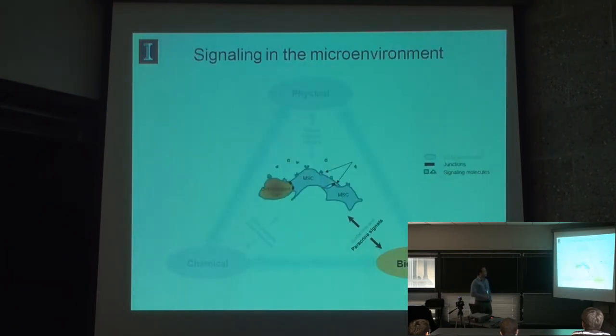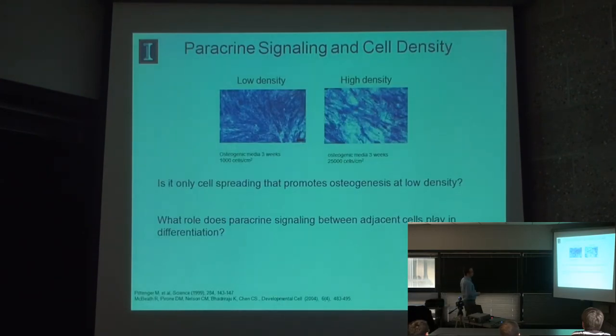Okay? So we thought this was really interesting, and so how can we utilize micropatterning to explore this further? And so we went back to this argument that the spreading of the cell influences osteogenesis. And I think a lot of biologists, and many I'd spoken with, felt this way, still believe that paracrine signaling is very important and is likely to play a significant role in these different density cultures. And so to remind you, at low density seeding, you get a high degree of osteogenesis, shown here with the blue. Well, when you initially seed at high density, you get a low degree of osteogenesis. And Chris Chen and others suggested this was because of this mechanical aspect of spreading.